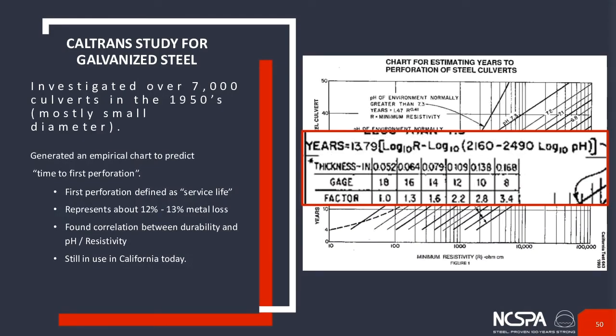And what they came up with was a service life definition of first perforation of the metal. And that represented, in their estimation, approximately 12 to 13% of the overall metal loss within the pipe. Now, this is going to be primarily concentrated in the invert of the pipe. Typically, the soil corrosion is not a factor, but it's the invert that experiences most of the corrosion. So again, this is what they found: this was driven by pH and resistivity. So this is the bedrock of the calculations that everyone uses for service life for galvanized pipe.